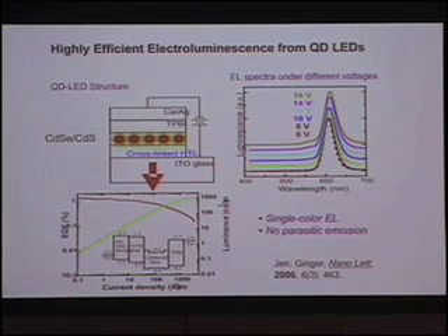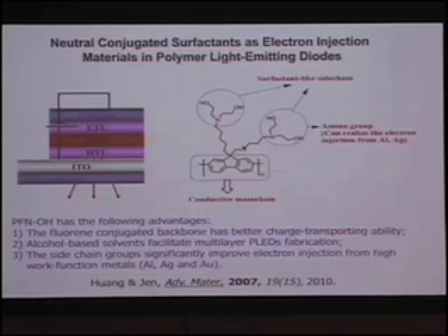The beauty of this is that when you have a cross-linkable hole transport material, it allows you to build a cascade for your hole injection toward the very low-lying band of your quantum dot. As a result, electrons come from here, holes come to here, and you have very well-confined exciton formation on your quantum dot. Then you have a very beautiful, narrow emission from that. So this is one very efficient LED we made.